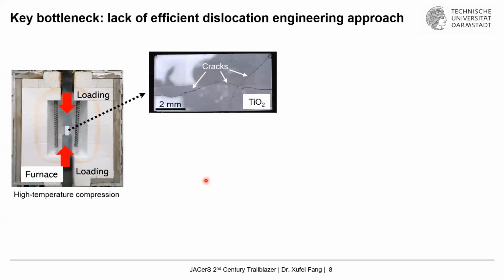As I mentioned, the key bottleneck to achieve the dislocation technology mentioned before is to have dislocations successfully engineered into ceramics, which are very often brittle, especially at room temperature. So currently, there seems to be a lack of efficient dislocation engineering approaches. Even with high temperature deformation, as we can see, sometimes it does not really guarantee a successful deformation of the single crystals.